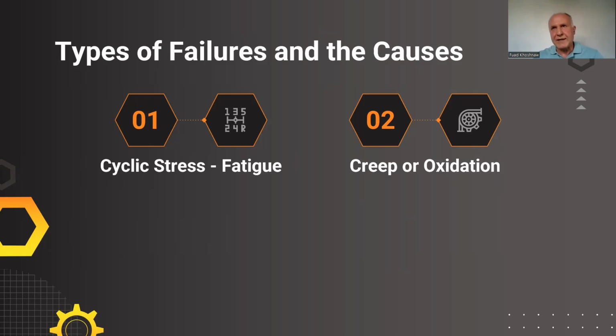And in general, it is not a fixed term, but in general, if the applied temperature with stress is around 0.5, half of the melting point, then at that time we need to consider creep failure. So if the material has a melting point, let's say 1000 degrees centigrade, then 400, 500 is high temperature.